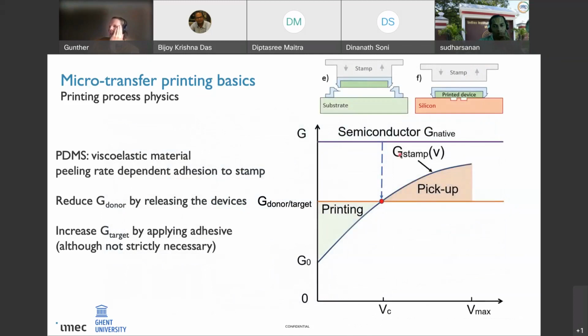Now, how does the pickup and the printing process work? Well, the basic idea is that we exploit the viscoelastic properties of PDMS. And that means that if you laminate PDMS against a material, the adhesion between the PDMS and the material will depend on how fast you peel off the PDMS from the material. The faster you peel it off, the stronger the adhesion is between the stamp and the device. This is shown here in this graph, where we plot the adhesion between the device and the stamp as a function of the peeling rate.